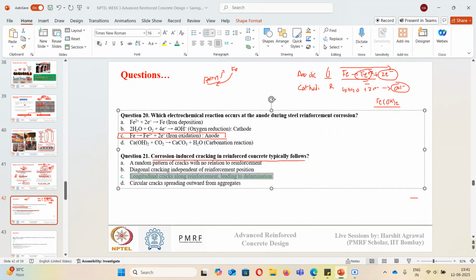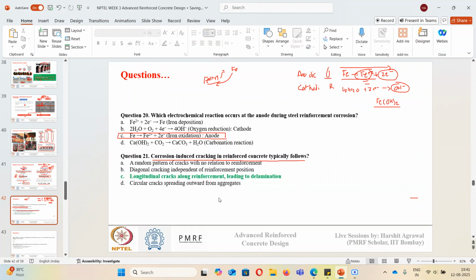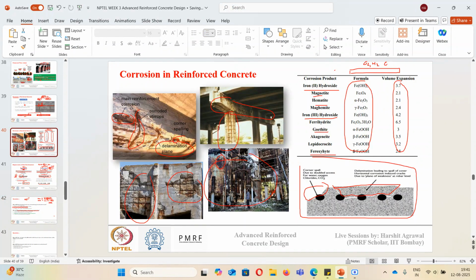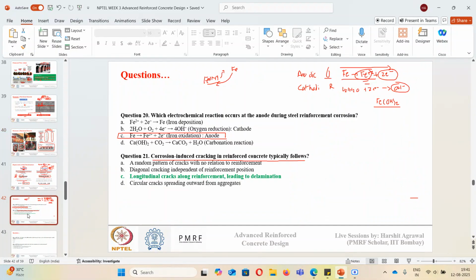So for 21, the answer is C. When we talk about corrosion, the cracking is a longitudinal crack that occurs along the reinforcement length. In all these cases, if you see, there are longitudinal cracks generated. Like in this image, you can see longitudinal cracking that led to spalling and delamination. The same thing you can see here also. It is a longitudinal crack that is generating.